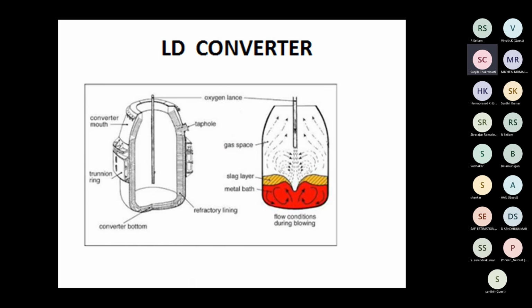So this is the LD converter. You will see this is a very useful converter. The LD converter is for the steel plant, where the material from the blast furnace is used for reduction of the carbon, from around 4% to 0.12, 0.13, depending on the situation. Here you see the picture is of oxygen lancing, where you are giving oxygen through the lancers.